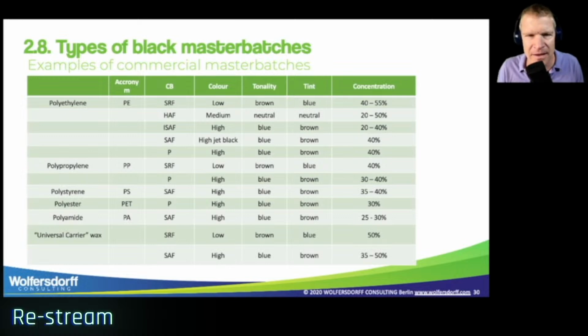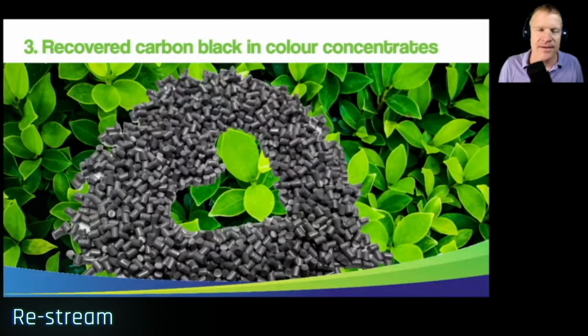We can see the tonality, and as mentioned, bigger particles, so semi-reinforcing or low color carbon blacks have a brown tonality, but in the tint they get a bluish undertone. And we have varying concentrations. That depends on the resin, but that depends also on the carbon black. Now, we have talked about recovered carbon black and we've talked about master batch. Let's talk about recovered carbon black in master batch.